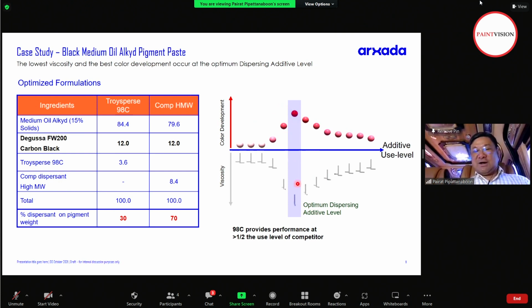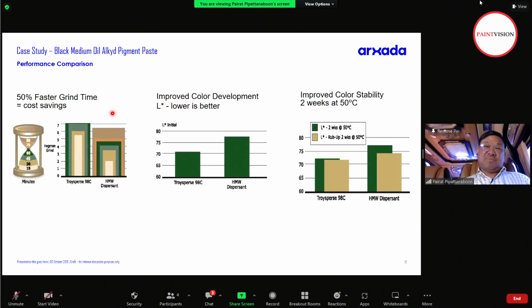So after running this pigment dispersion demand optimization, we came up with 50% faster grind time. If you need to reach Hegman number 7 with 98C, you only run about 45 minutes, compared to the high molecular weight type, where you have to run up to about 90 minutes. You improve color development. It's a carbon black, so consider the lowest L value. And also after 2 weeks at 50 Celsius, we take out the stored sample after the stability test and run this color development test again. This also shows you a very narrow gap of delta L, and still a good stability of the L value.